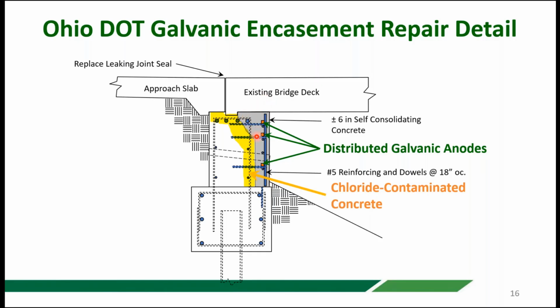So they removed the existing damaged concrete, but they did not remove all of the chloride contaminated concrete in the pier. And because they weren't doing that, they knew that if they did this refacing, the refacing would be fine, but this steel back in here would all continue to corrode and would fail the refacing after a short period of time. So they put in the anodes to protect the steel that remained in the salt contaminated concrete that was left in place.